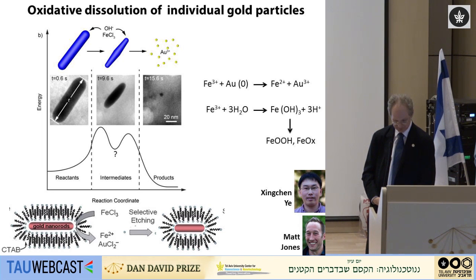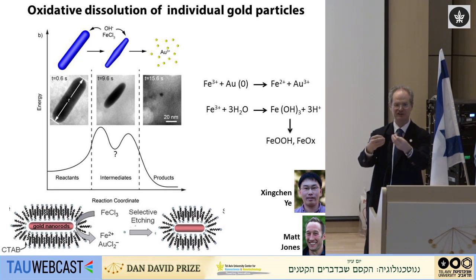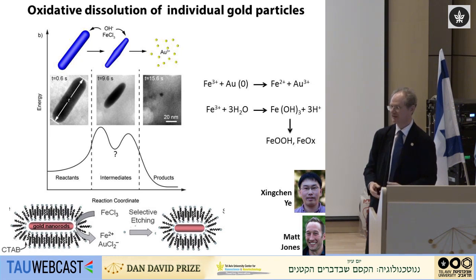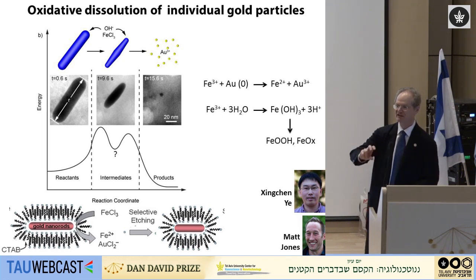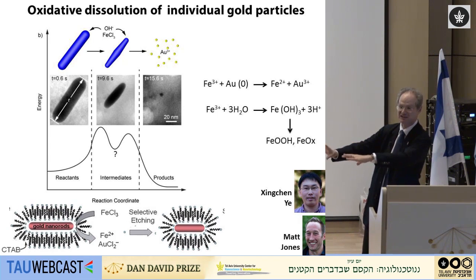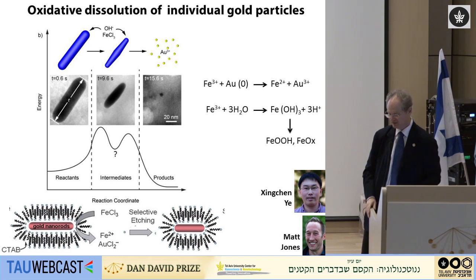But another thing that we can do: we cannot yet make all those shapes, the stamp collection that I showed you, in the electron microscope. We've been trying, but we can't vary the temperature and the concentration as a function of time as intricately inside the electron microscope as we can in a flask that's controlled outside. So we can't quite make all of those shapes, but what we can do is take shapes that have been made in advance and make them go away by etching them. So here is an example where we have an etchant, in this case an iron 3+, that will etch a gold nanoparticle. And you can see that if we expose it to etchant, then the gold nanoparticle is slowly dissolved.